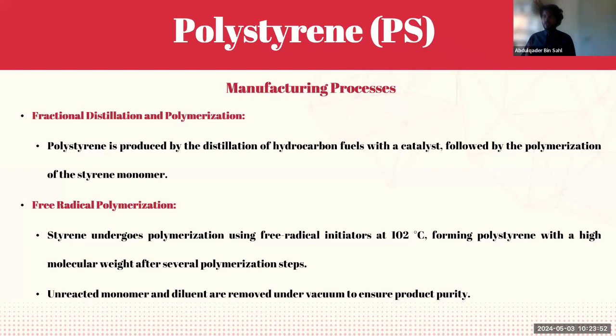Then we go to free radical polymerization, where once we have the styrene monomer, it undergoes polymerization. So this occurs at a controlled temperature of about 102 degrees Celsius, using free radical initiators. So this method is pivotal in linking monomers together to form long chains of polystyrene, resulting in a polymer with high molecular weight. So the process doesn't end after polymerization. To ensure the purity of the final product, the unreacted monomer and any diluents are removed under vacuum. So this step is essential to maintain the quality and characteristics of the polystyrene produced, ensuring it meets the industry standards for various applications from packaging to building and insulation, and so on.